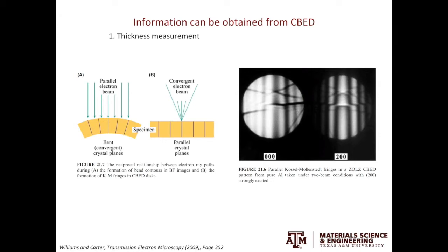In the first case, we mentioned there will be bright and dark fringes. Similarly, in the second case, we also expect to see bright and dark fringes. And this is exactly what you see in the CBED pattern on the right. There is a quick note on this. In order to see the bright and dark fringes, the specimen has to be fairly thick and the electron beam undergoes dynamical diffraction.